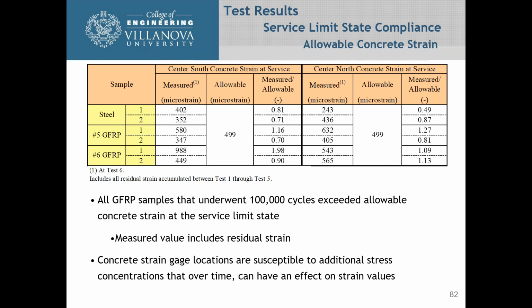Here's a summary of all the ratios, and this is the concrete strain at the center of the sample, essentially at the center support at the bottom. The allowable was 499, and you can see that some of the ratios are below 1, some of them are above 1. There's one outlier that's 1.98.